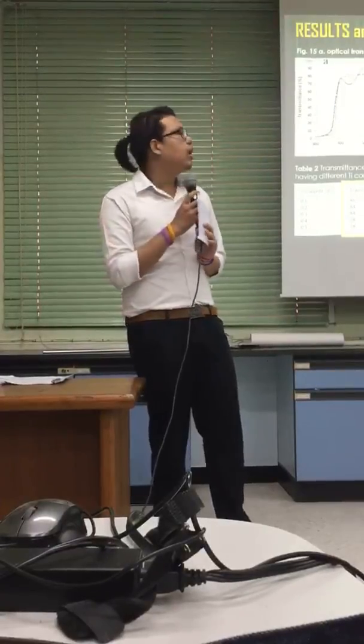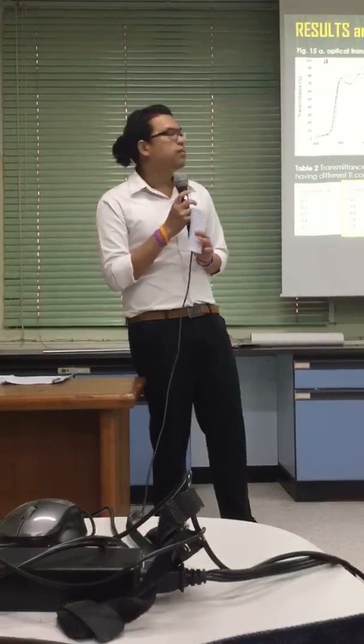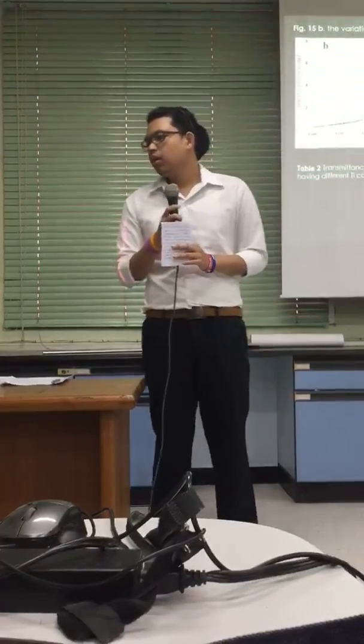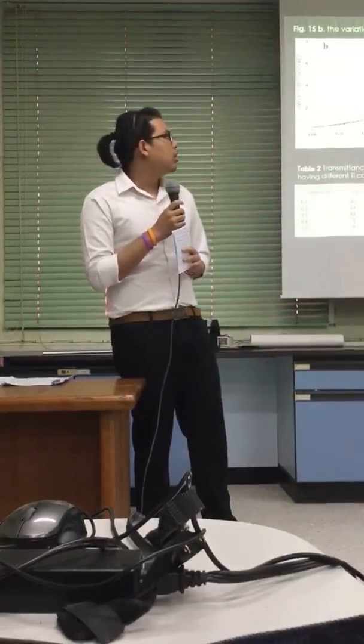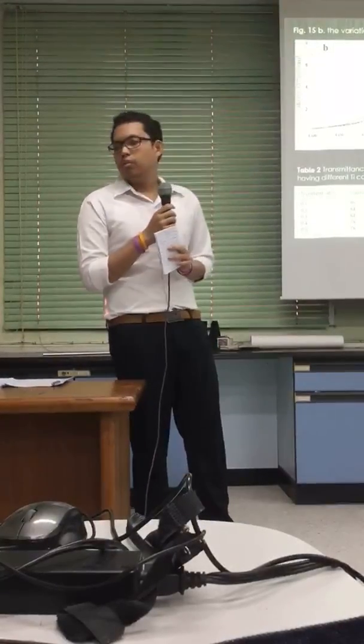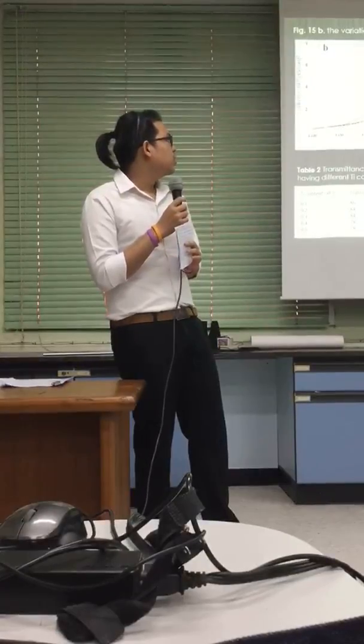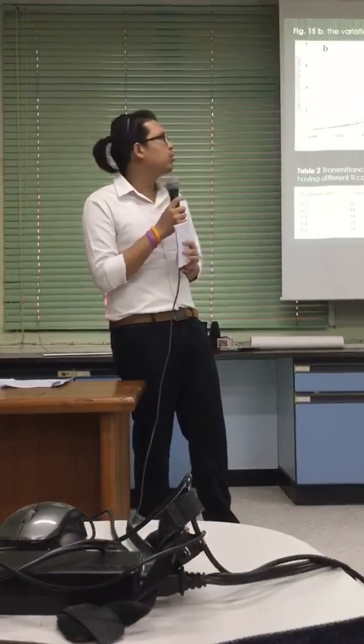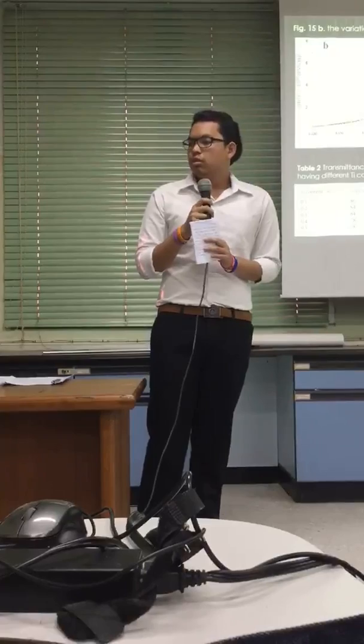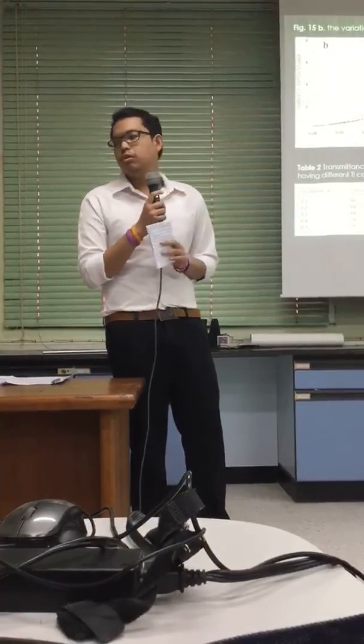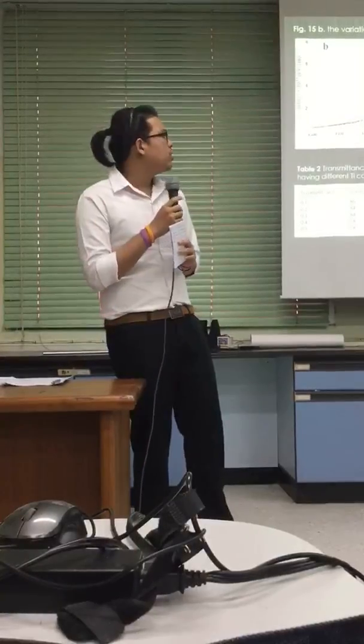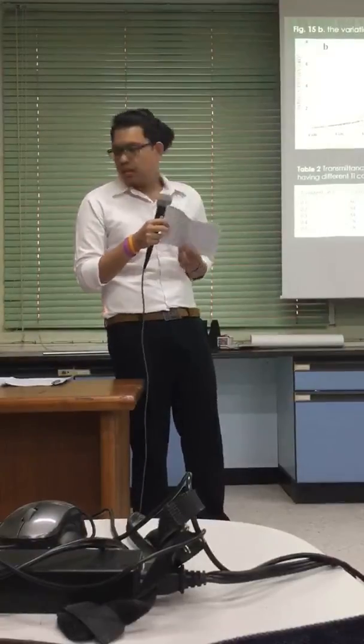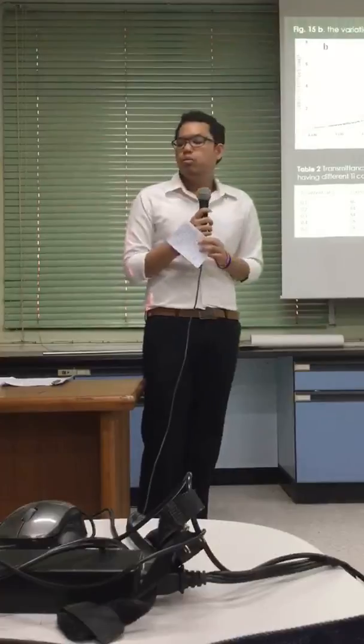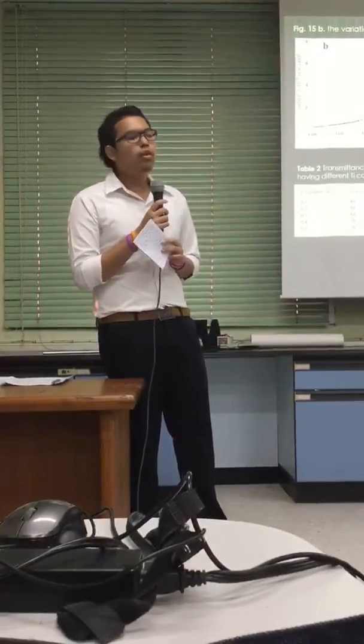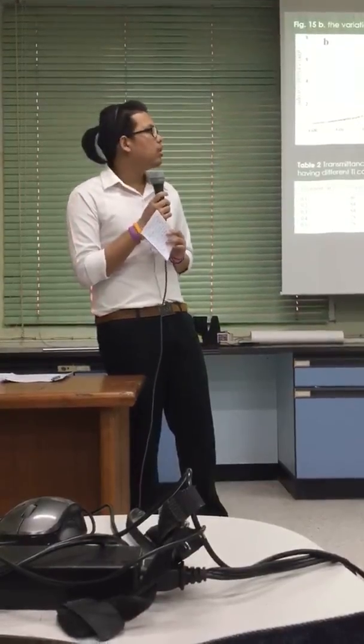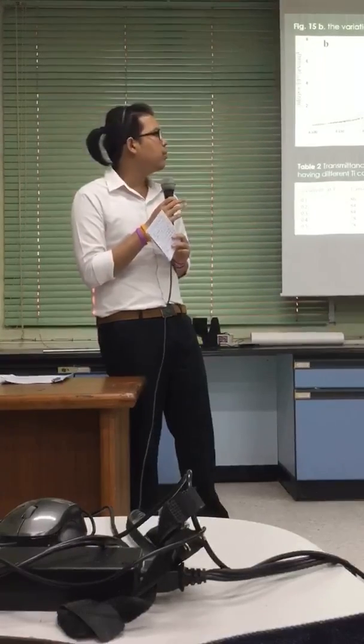And we can use this formula to find absorption coefficient, using transmittance in these formulas. Next, about optical properties, we can find optical band gap using Tauc model with absorption coefficient equal to 0, shown in Table 2. And Figure 15b shows the relationship between absorption coefficient and photon energy in absorption regions. This widening, called Burstein-Moss effect, is the result of filling electron states near the bottom of conduction band and makes Fermi level lie in conduction band.